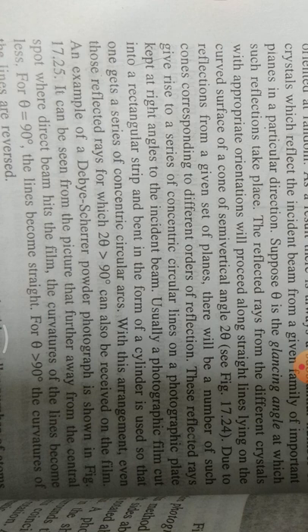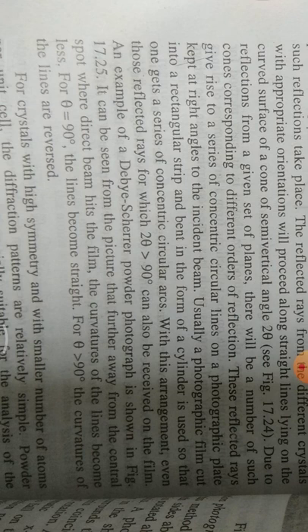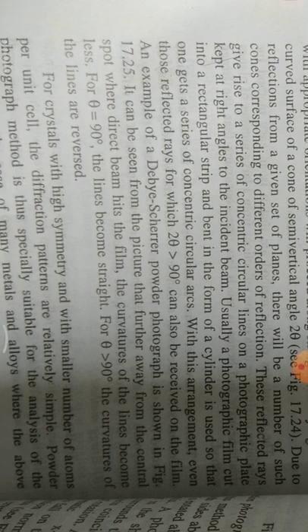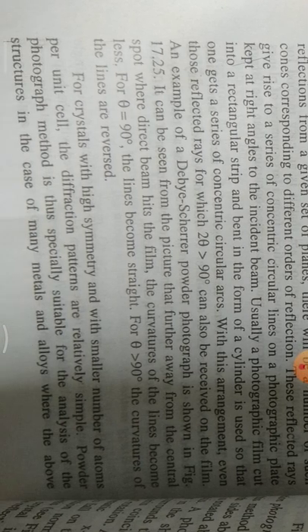Due to reflections from a given set of planes, there will be a number of such cones corresponding to different orders of reflection. These reflected rays give rise to a series of concentric circular lines on a photographic plate kept at right angles to the incident beam. Usually a photographic film cut into a rectangular strip and bent in the form of a cylinder is used, so that one gets a series of concentric circular arcs.